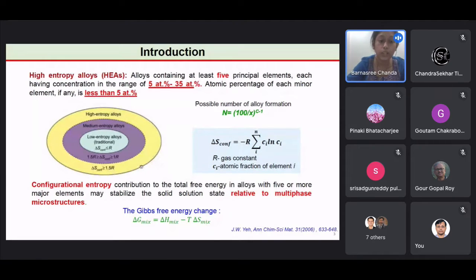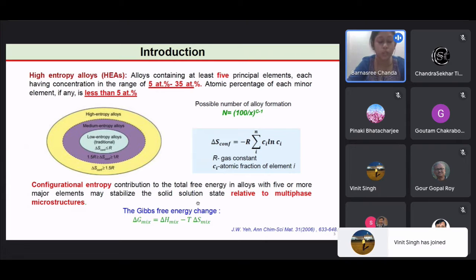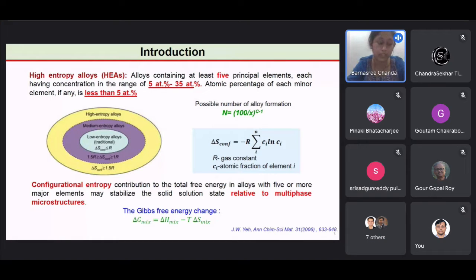Low entropy alloy has configuration entropy less than or equal to 1 R, for example, low alloy steel. Medium entropy alloy has configuration entropy in the range of 1 to 1.5 R, for example, cobalt-based superalloy and nickel-based superalloy, and then high entropy alloy. Basically, the high configuration entropy, by lowering the total free energy, stabilizes the solid solution phase. Therefore, it restricts the formation of expected intermediate phases.